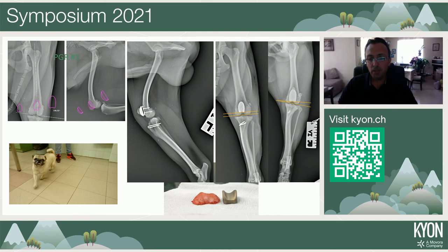A little bit of criticism could be made in this case because we are able to compensate a little bit of this deformity. For example, this wide distal femoral varus could be compensated by positioning the trochlear prosthesis in a little bit straighter way, which I definitely didn't achieve in this case. But if you compare to the second X-ray on the right, this is another case where this was achieved by just a straighter position of the trochlear prosthesis.